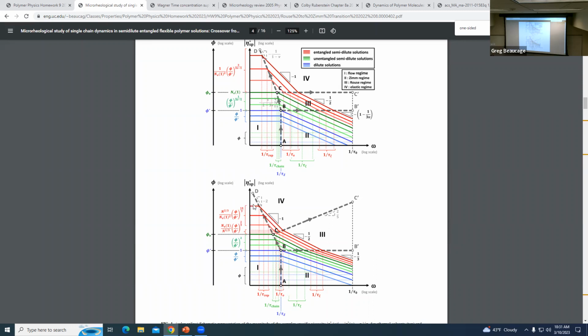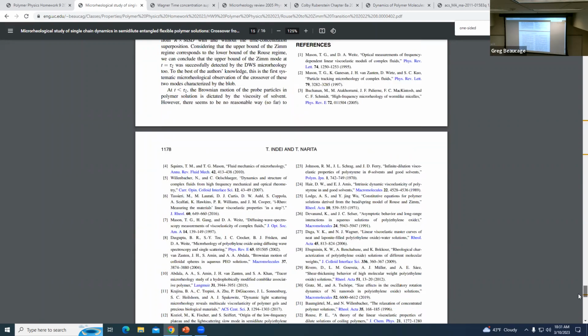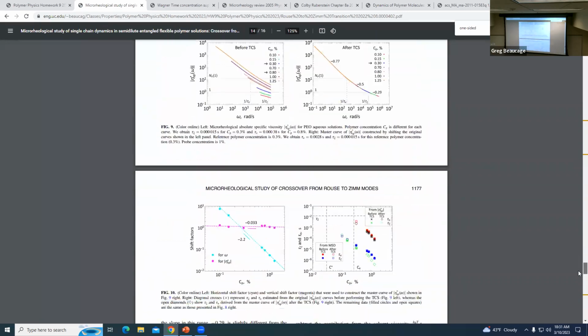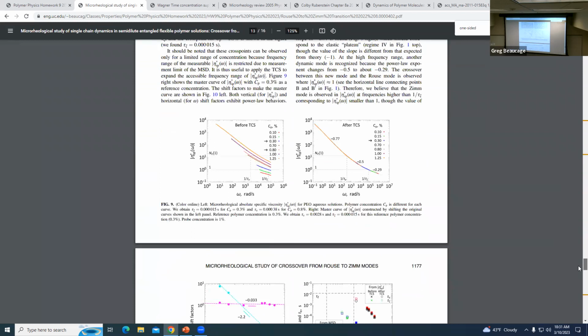And then it goes to just bulk motion of the fluid, like the Einstein kind of flow, all within a polyethylene solution. You can see that it's complicated. It's not simple, right? So anyway, he shows that. Figure 9 shows that. In the end, he demonstrates exactly that at figure 9. So this should be 1/3, it's 0.29. He says good enough. Then he gets the 0.5 for the Rouse part. That's exact. Then instead of 1, he gets 0.77. He says good enough. Right.